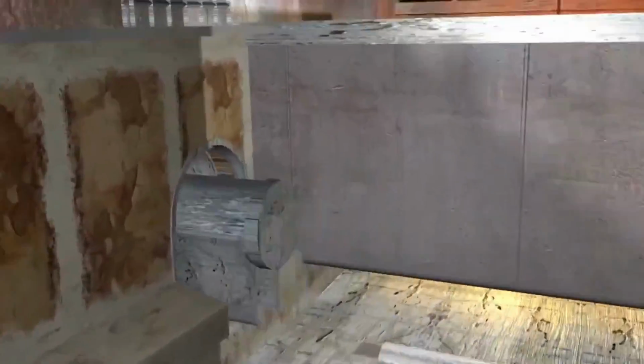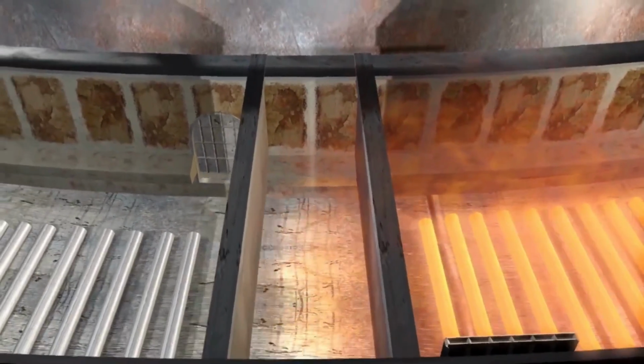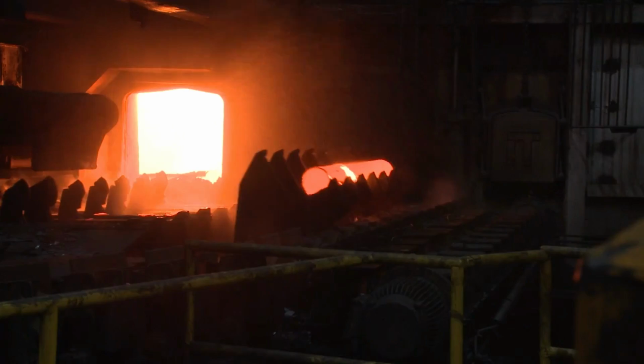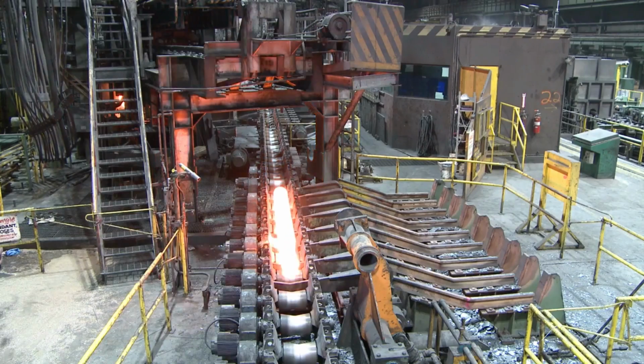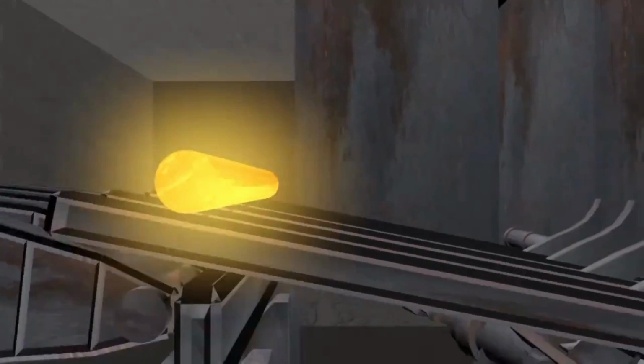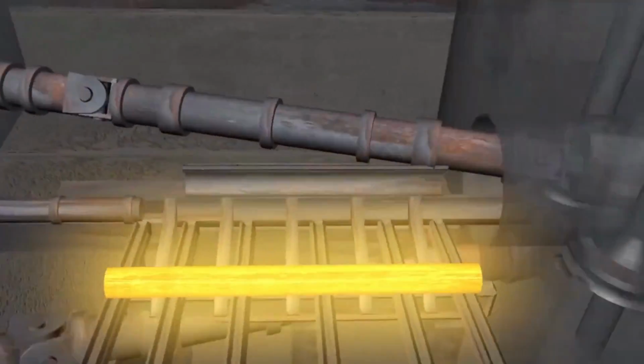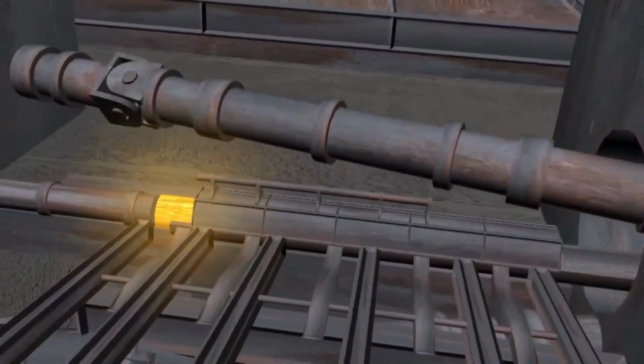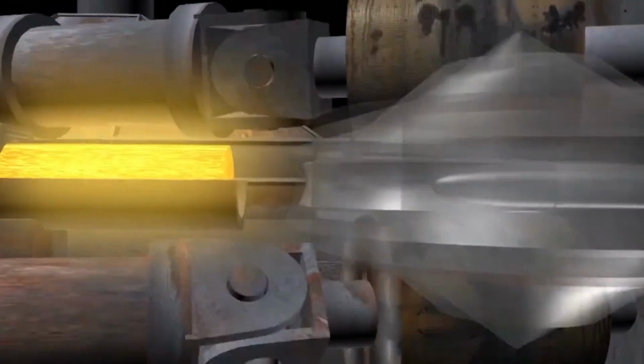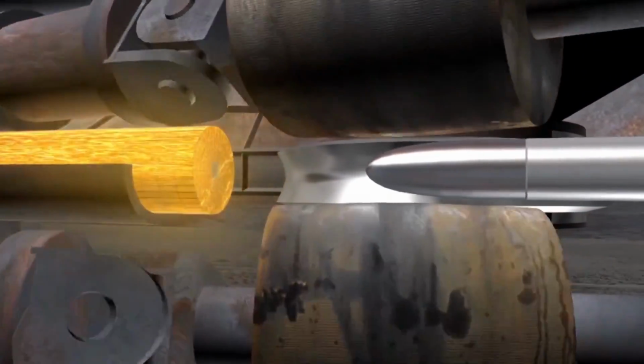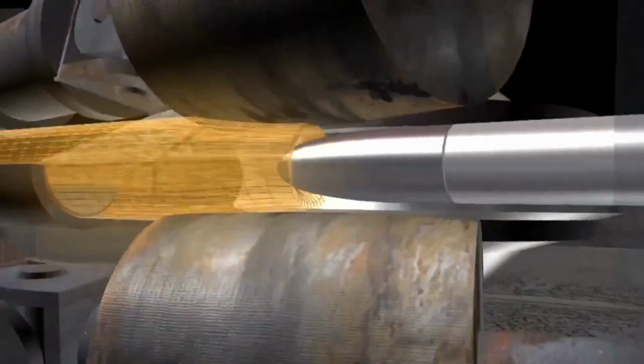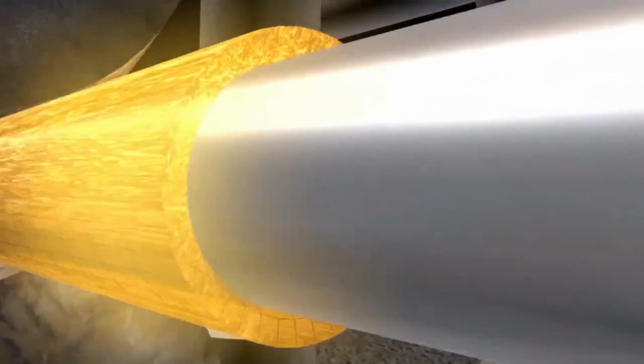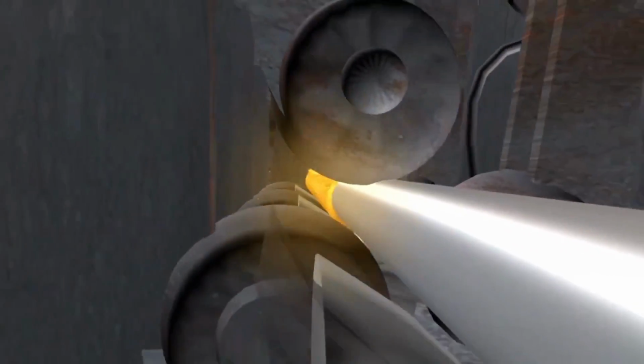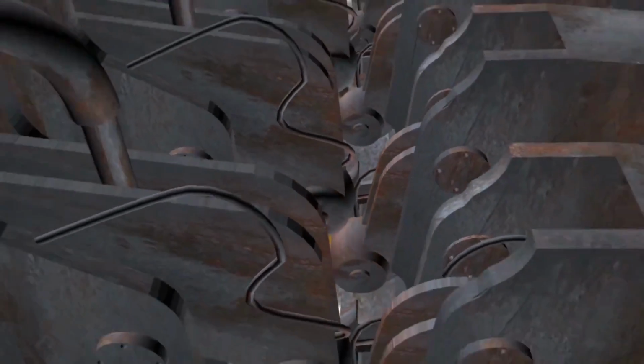The furnace floor rotates clockwise and the billets are heated to approximately 1300 degrees Celsius. The heated billets are removed from the furnace one at a time and transported to the rotary piercer, where the solid round heated billet is converted to a hollow shell by cross-rolling over a high alloy piercing point. This cross-rolling action generates alternating tension and compression forces in the core of the billet. These forces create a void in the center as it comes into contact with the piercer point.